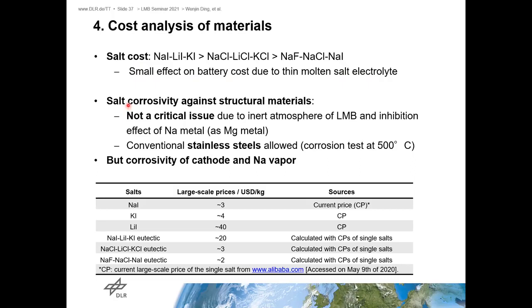And we have also considered the salt corrosivity against the structural materials, the metals or alloys. We find out that when the sodium metal has contact with the salt, it has a similar function as magnesium metal. It can reduce the redox potential of the salt and reduce the corrosivity of the salt. So we think it's not a critical issue, because the liquid metal battery is operated under an inert atmosphere, and also there is the inhibitor effect of the sodium metal.